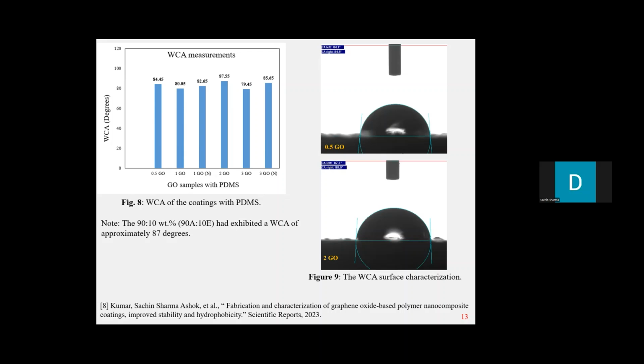So when we look at the water contact angle in figure 8 for all the samples with the inclusion of graphene oxide at different increments, the 2 weight percentage of the graphene oxide exhibited the highest value. Now, graphene oxide itself in nature is hydrophilic, and it was reported that graphene oxide exhibited a water contact angle of approximately between 60 to 70 degrees. So over here, with the inclusion of PDMS, it actually enhanced the value close to having a hydrophobic nature. So among all the samples, the 2 weight percentage graphene oxide exhibited the highest result.